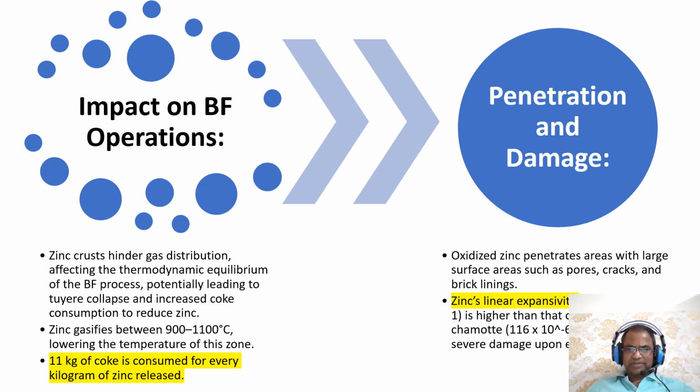This causes an unsymmetric condition of the furnace as far as the burden descent is concerned, and once an unsymmetric condition in the stack occurs, there is non-uniform gas utilization across the blast furnace. This severely hampers the final melt out and the consistency of the process.